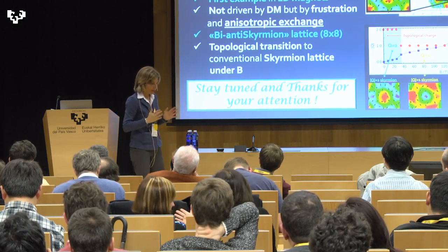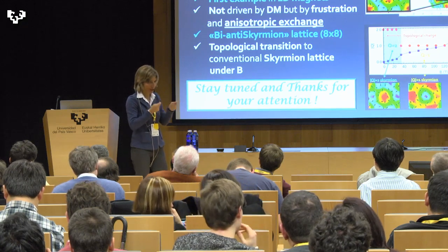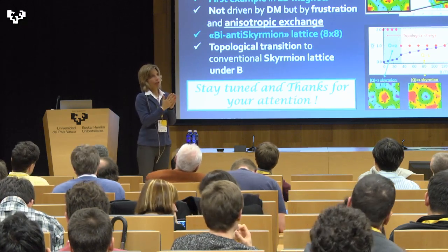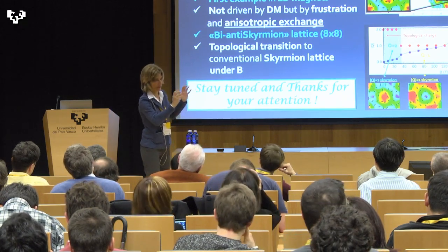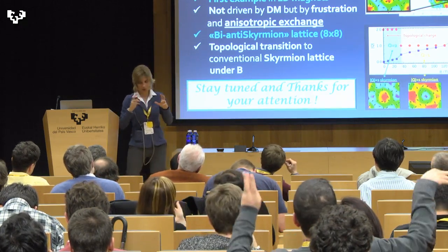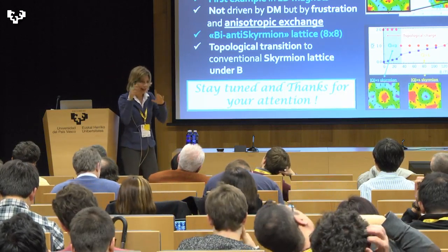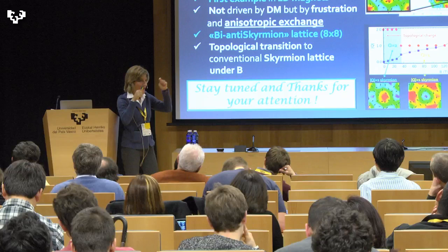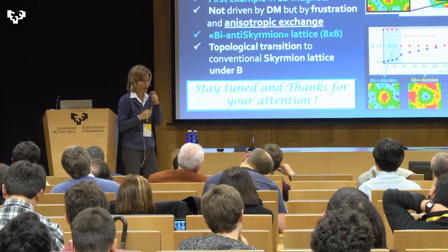If we do some other simulation, tuning the parameters artificially, for example, if you reduce the frustration, the skyrmion gets a little bit bigger. Certainly the size is related to this, but we don't have a complete phase diagram of all the JZY and J3 over J1.